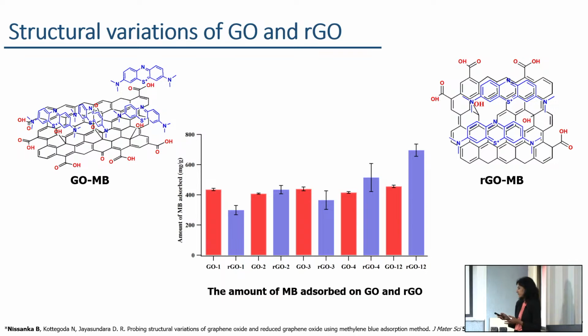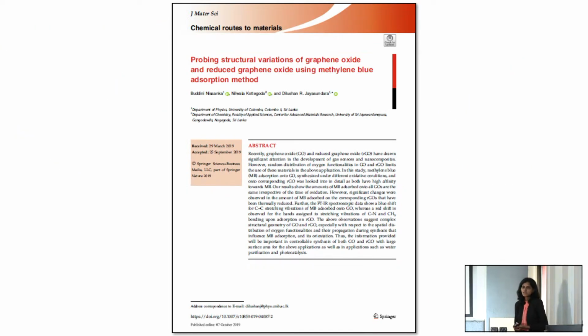When comparing the amounts of methylene blue that adsorb onto these reduced graphene oxide samples, the RGO4 and RGO12 samples show high methylene blue adsorption. This indicates larger graphitic basal planes in these RGO samples. Therefore, the findings of this research provide valuable information to synthesize graphene oxide and reduced graphene oxide with controlled oxygen functionalities and larger graphitic basal planes. This is highly important for applications in the development of functional coatings, electrode materials as well as nanocomposites. At the end of this study, I was able to publish these findings in the Journal of Materials Science.